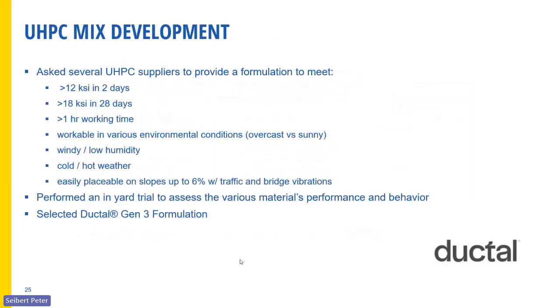The other thing we had to do for this project specifically, because it was the first time now of this large scale, we as the contractor had requirements to the supplier. We needed them to make sure we can get 12 KSI in 2 days, to 28 days, get the 18 KSI, but also we required from them 1 hour working time. The reason being is, as you saw, the batch plant is at the bottom of the bridge, and we had to move the material all the way across in these dumpers. It takes about 20 minutes to drive across there. So you basically have material sitting in the dumper that's not being agitated.